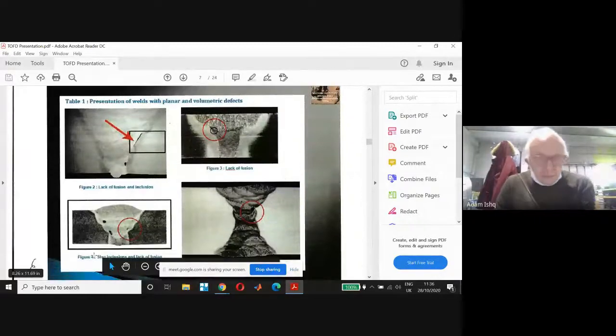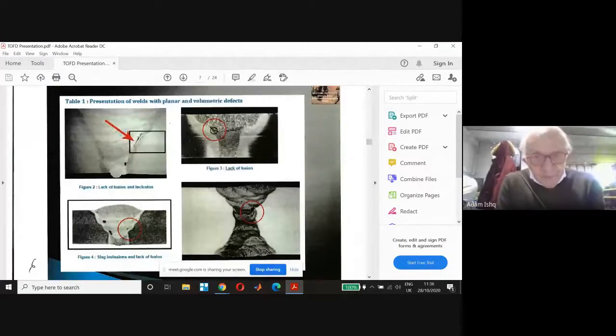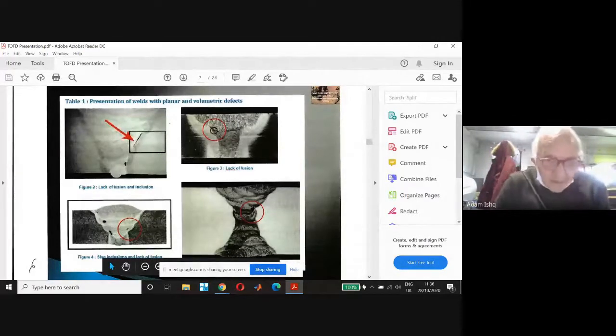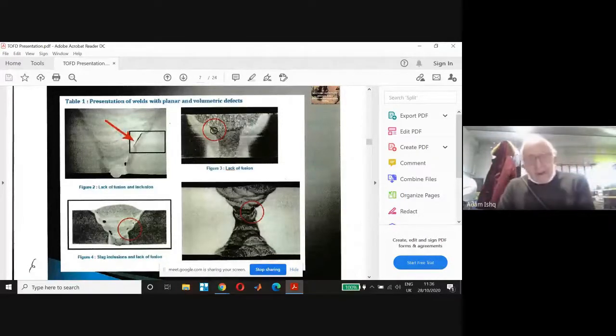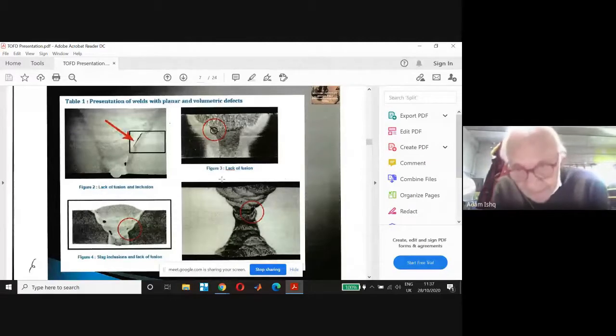Okay, yes. Now you can see some types of defects. At the left, the first is a typical lack of fusion, a planar indication. Generally, you cannot accept planar indications in the weld. Upper, you see a hole, that means porosity, slag inclusion. Slag inclusion and porosity are volumetric indications, and are more acceptable in the code. Again, in the right upper, you can see lack of fusion. Again planar, you see different orientation. So for time of flight, very easy. If you use standard ultrasonic technique, then it's a little bit of a problem. A big defect like this, when you look with ultrasonic, if it is oriented, you may miss it. On the right again, you see lack of fusion between multipass weld. Next slide.